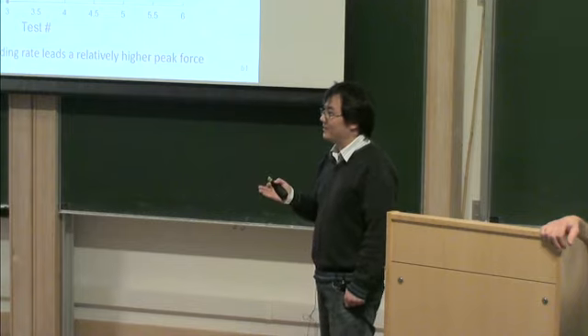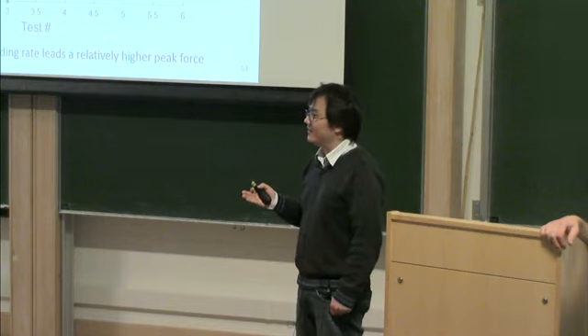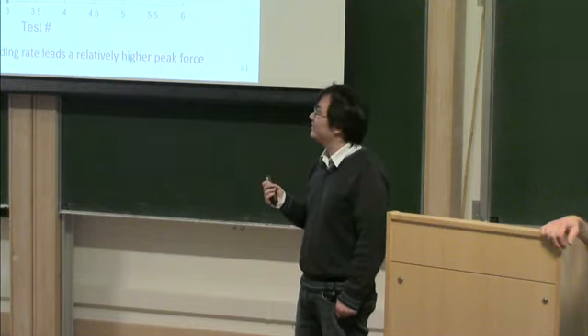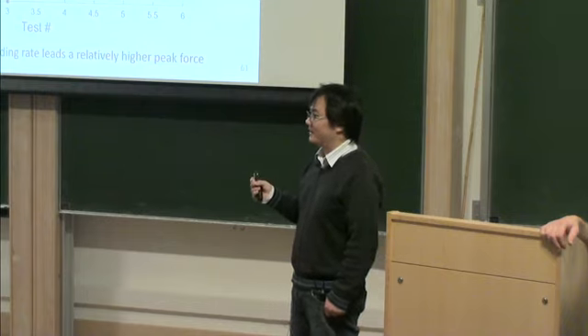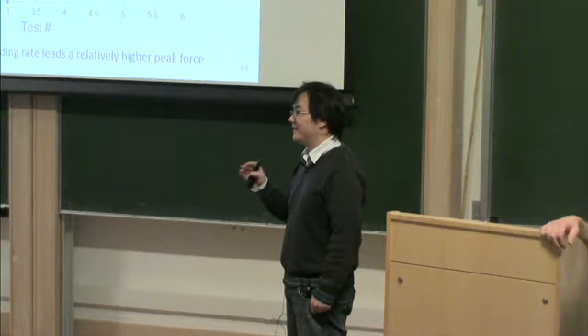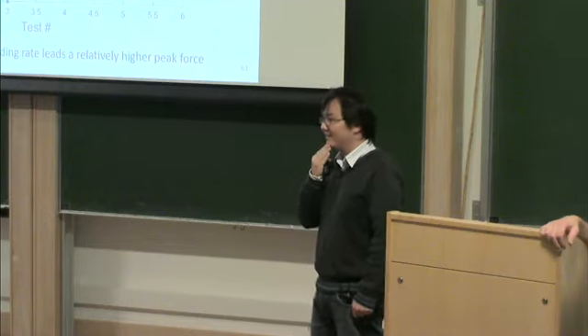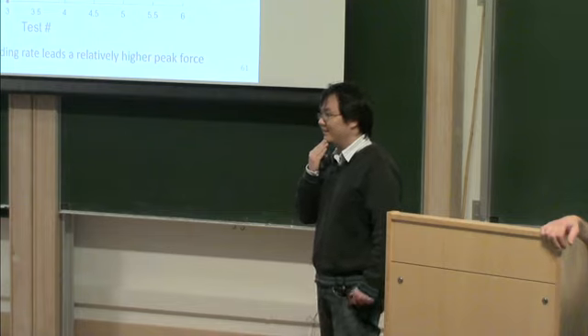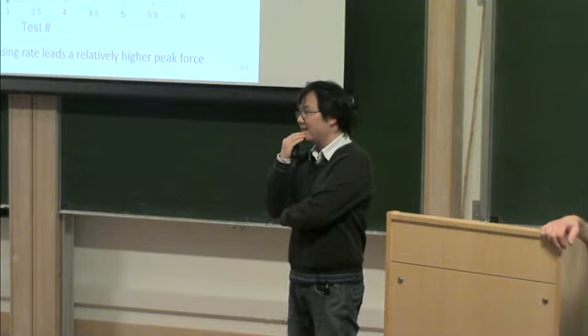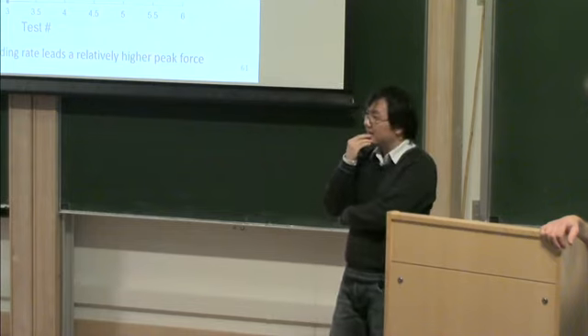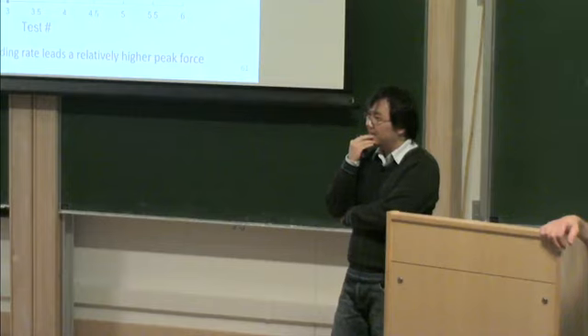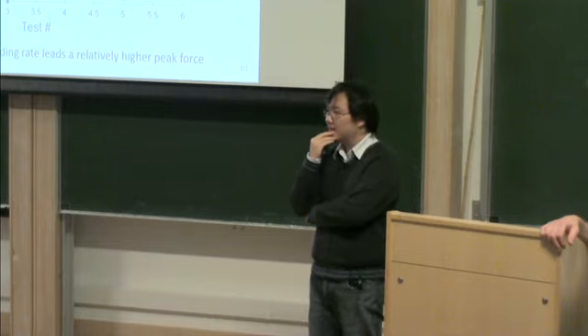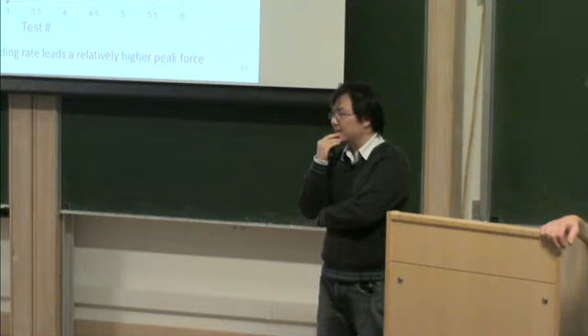That part of work John has done in 1998, right? You were trying to use the linear elastic, linear cohesive fracture mechanics to match your result. It turned out the linear elastic is not really matching up. Not use linear elasticity. You need a viscoelastic cohesive crack model. So you've got to subtract from the total deformations the creep deformations, and then you can match the fracture deformations. And actually, in my talk tomorrow, I'll show the results of some Arctic and Antarctic tests. That is a preliminary to what Wenjun must do.